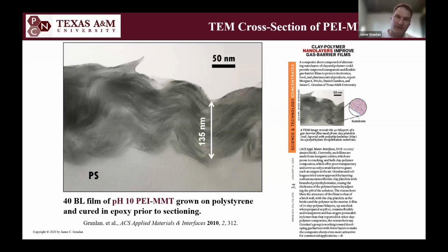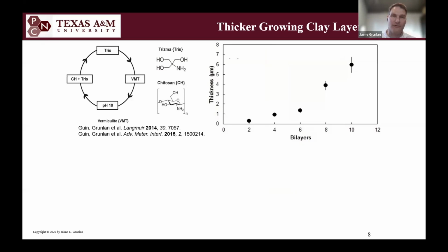A real life nano brick wall is on the screen now, and it's a 40 polymer clay bilayer film. Bilayer means one polymer and one clay layer paired together, anion and cation. You can see that it's only 135 nanometers thick, even though it's 80 layers. So they're just 1 or 2 or 3 nanometer thick layers. It's basically monolayers of clay and monolayers of polymer. And it makes this tortuous path for gas molecules, so it becomes a very high gas barrier. But as I mentioned, it's very thin.